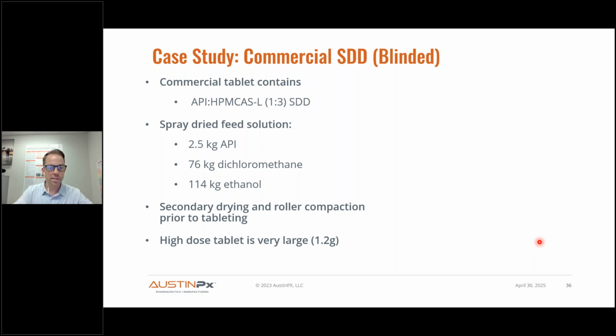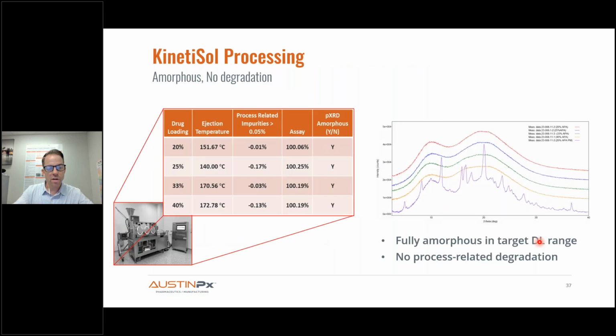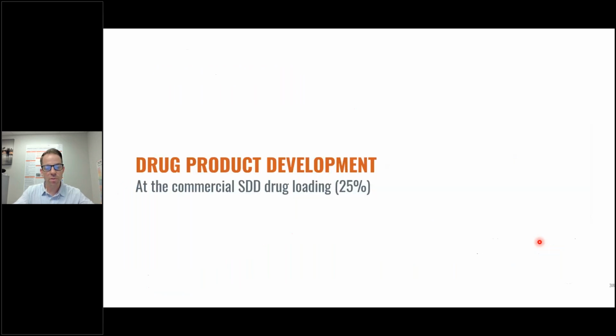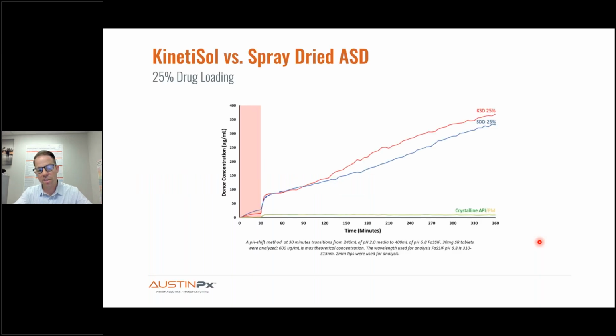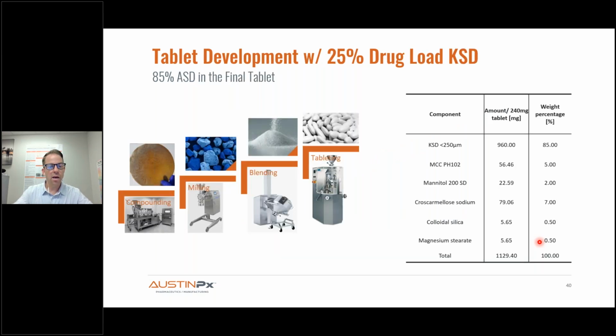As with all SDDs, secondary drying and roller compaction is required. The high dose tablet is very large, 1.2 grams. So spray drying was limited to 25%, but when we were working with this molecule, we were easily able to generate amorphous solid dispersions between 20 and 40%. But we started with drug product development matching the SDD drug loading at 25%. We were once again able to leverage our biopharmaceutical tools to show similar dissolution performance to the SDD. We took it through our tableting process. We were able to get 85% ASD load in the final tablet. So we were able to generate the high dose tablet with slightly smaller size, 1.129 grams relative to the 1.2 gram SDD tablet.